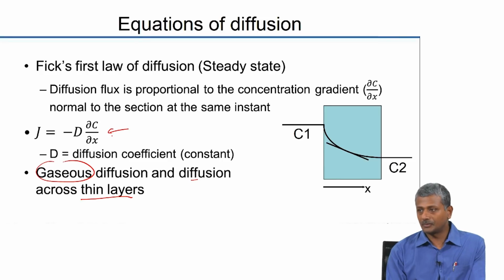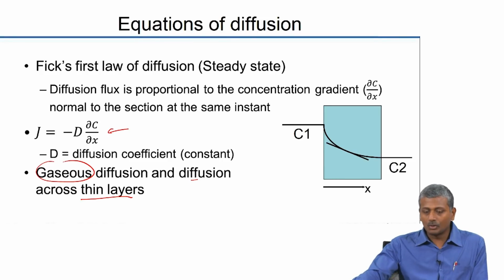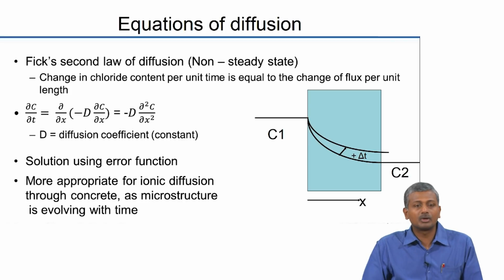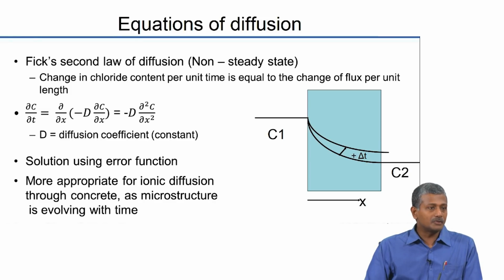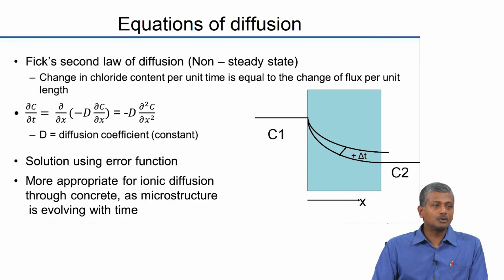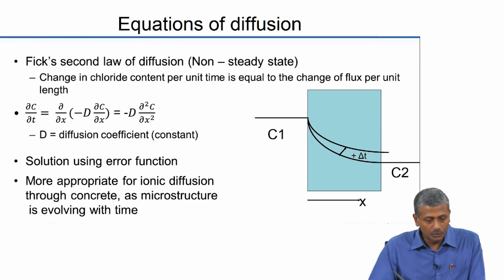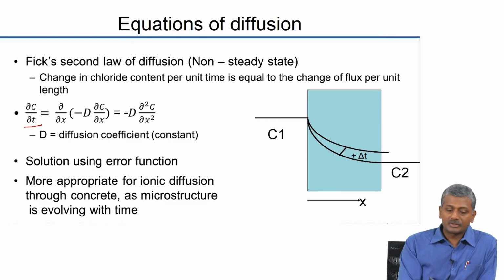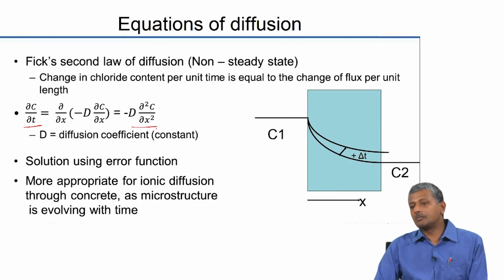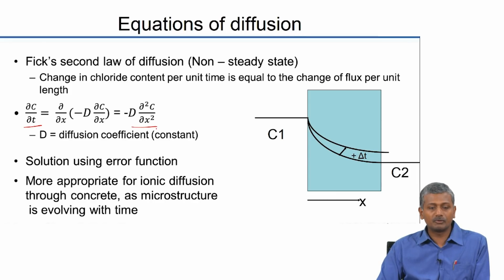Now when you come to concrete, we know very well that with time the properties of concrete undergo changes. With additional hydration, the structure of concrete develops even more, and because of that you have a change in the rate at which the diffusion can happen as time progresses forward, okay. Because of this, we cannot apply a steady state condition to concrete and we go with a non-steady state condition, and in this Fick's second law of diffusion is used, and you have the time variability of the concentration related to the spatial variability of the concentration by a diffusion coefficient.